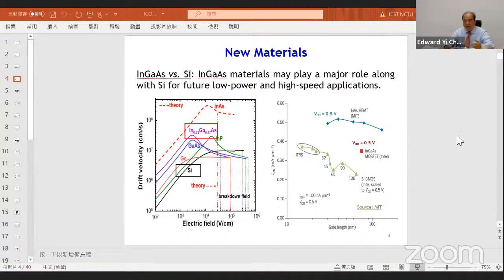In this work, we use InGaAs as the material, because InGaAs has much higher mobility than silicon that allows you to have a higher drift velocity and low electric field. So using this kind of III-V material, you can have higher speed with low energy consumption. On the right-hand side, you can see the Ion of the InGaAs device at different gate lengths. This Ion is much higher than silicon-based material, which means it will have a higher speed when you use it as a logic device.